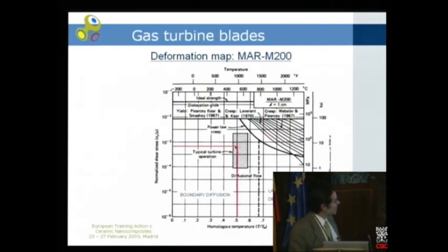But suppose that we want to obtain an even better material. So which is the creep micromechanism acting at this point? You can see that it is the same. It is diffusional flow, and in this part it is boundary diffusion. So there is diffusion along these boundaries. So how can we cope with this problem?